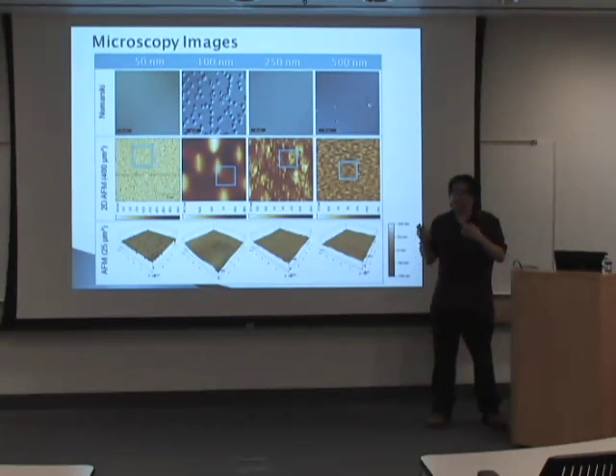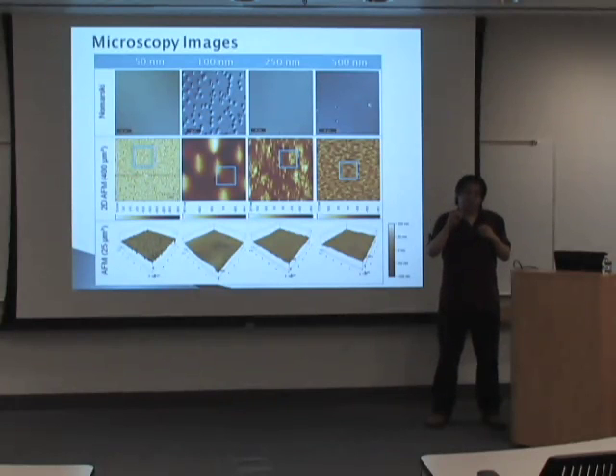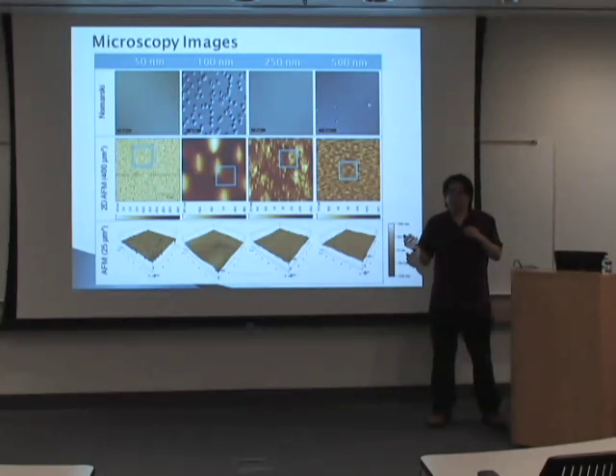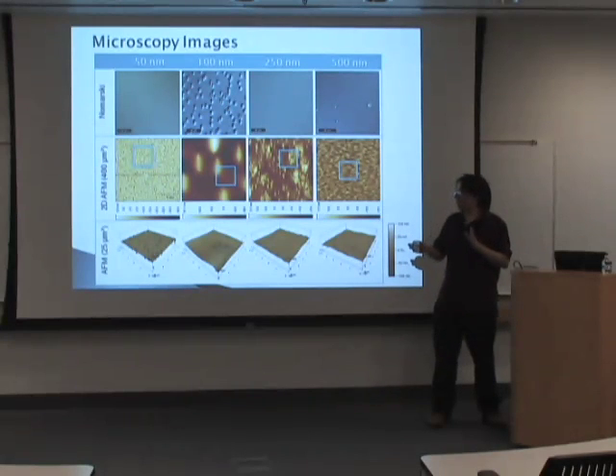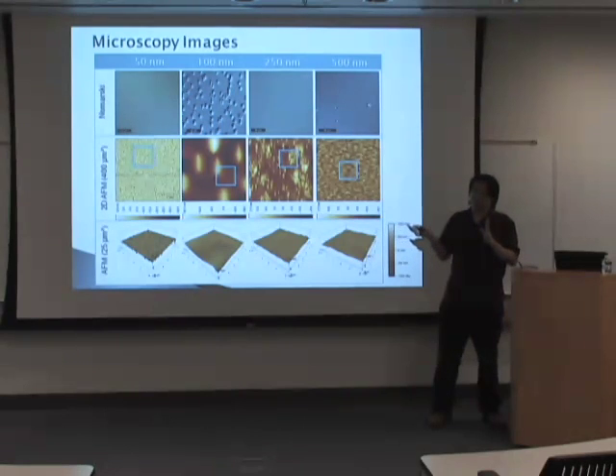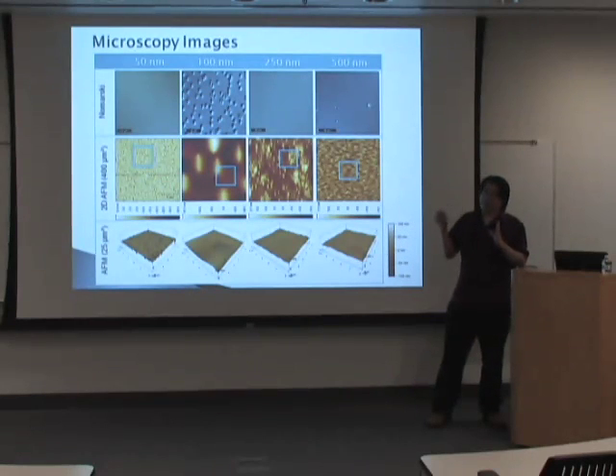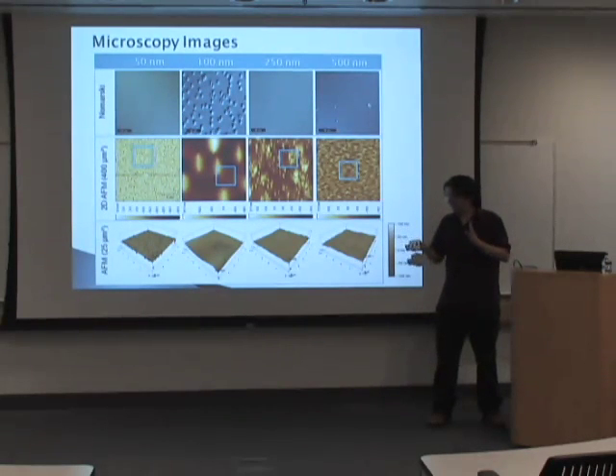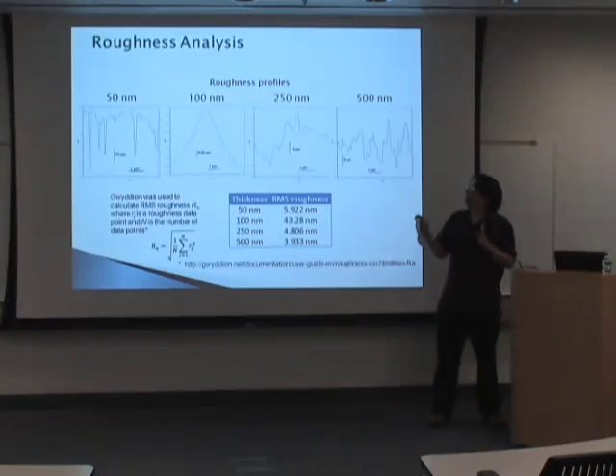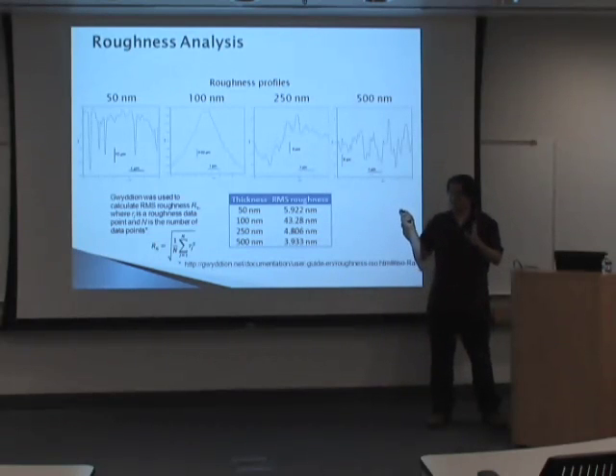You can see it on the 50 nanometer one. There are a lot of these pits. These are the dislocations that I mentioned, and you can see that the number of these pits gets less and less as your thickness grows thicker and thicker. So we can see a correlation between the roughness and the thickness, and we can also get a further view of this roughness by doing some roughness analysis.